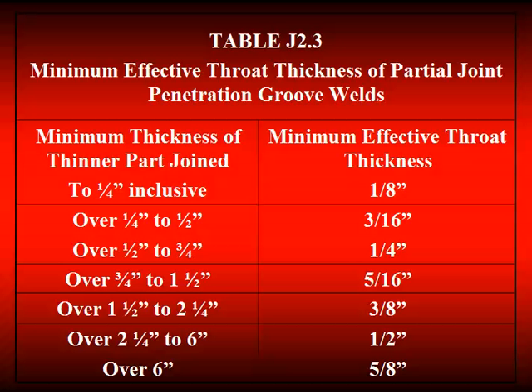And we also have in the code minimum size PJP groove welds, and those show up in table J2.3. And these are minimum sizes that are required regardless of the load transferred through the connection. Please don't take these minimum sizes to mean anything in terms of your design of the connection. This does not say that typically for loads transferred through the joint, this is the size of weld you need. You can't predict that. Rather, this has to do with the practicality of welding and how we make all the codes work together. So, for example, if I have material over 1/4 up to 1/2 inch, regardless of what design loads say, I need to put in a PJP with a minimum throat of 3/16.